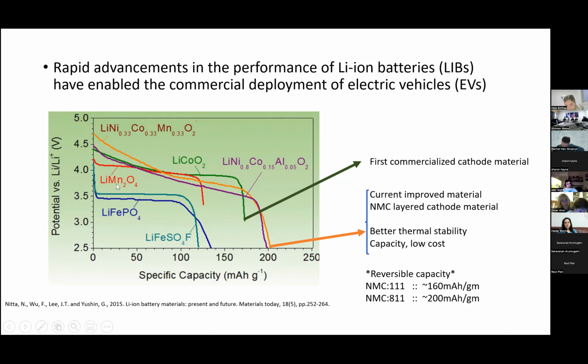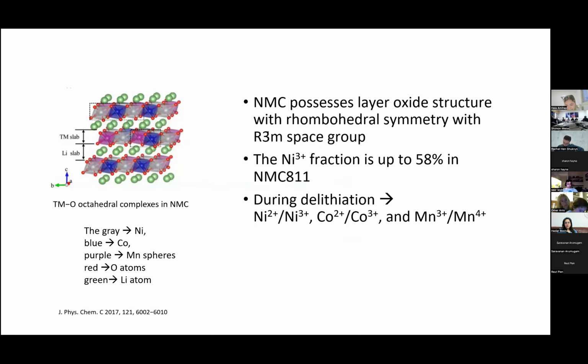So all the other materials are also competing with NMC, which is popularly commercialized now. NMC is attractive because of its thermal stability and low cost, as we are decreasing the percentage of cobalt. So the cost of the overall cathode has decreased. This NMC, which is nickel manganese cobalt oxide containing lithium, has rhombohedral symmetry with the R3m space group. Especially when we increase the percentage of nickel, it has higher redox ability and higher storage of lithium ions in the overall cathode material. When we remove the lithium from this cathode material, all these transition metals like nickel, cobalt, manganese go to a higher oxidation state in order to compensate the ionic charge balance.